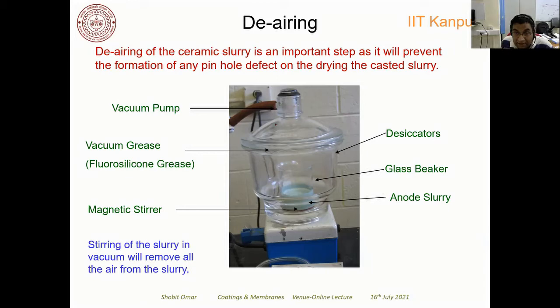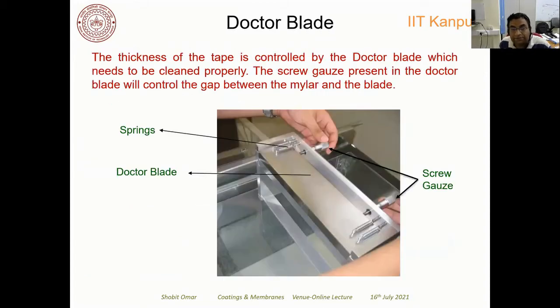What you do is you take a vacuum desiccator, and you put your slurry in a glass beaker, and you magnetically stir this slurry, and after stirring, you increase the vacuum, so you will see that the air will come out of this slurry. You have to do this for maybe 1 to 2 hours to take out all the air which is present inside the slurry through this vacuum process.